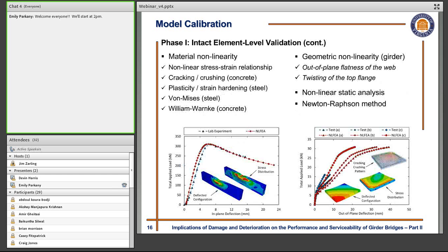For both of these models, we included all sources of material nonlinearity, including the nonlinear stress-strain relationship, cracking and crushing for the concrete, plasticity and strain hardening, and also appropriate failure functions for both of these materials. For the steel plate girder, we also included geometric nonlinearity to capture the local instability and the nature of these thin-walled structures by introducing the initial imperfection in the form of out-of-plane deflection of the web plate and also twisting of the top flange. We performed nonlinear static analysis using the ANSYS software and Newton-Raphson as our nonlinear solver. For both of these models, from the analysis, we extracted the results at specific locations of the specimen and compared them with those available from the experiment.